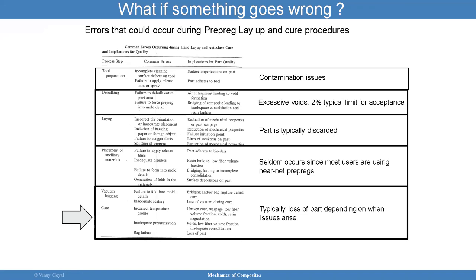Common errors occurring during hand layup and autoclave cure and implications for quality. So here you have the process step, the tool preparation. A common error is incomplete cleaning or failure to apply release film or spray. What is the implication? You will have surface imperfections if you don't have good cleaning, and you have undulations in the surface, which can decrease the strength of the composite. If you fail to apply release film, then the part you're making is going to be stuck. These are issues you want to look at, contamination issues, top level view.